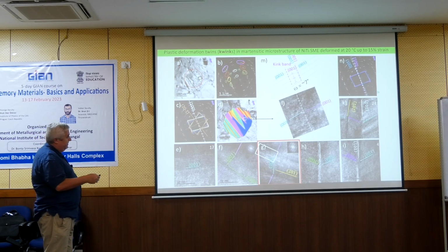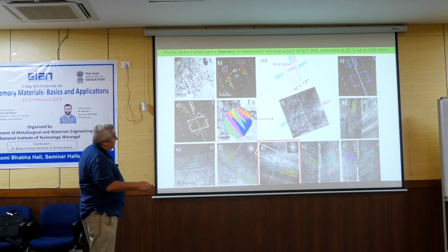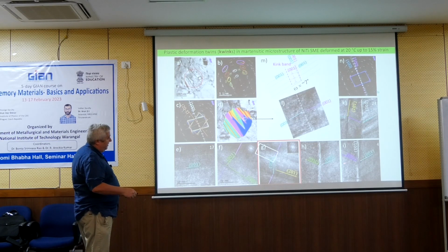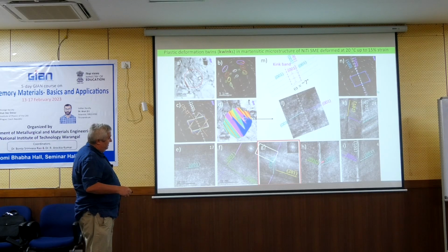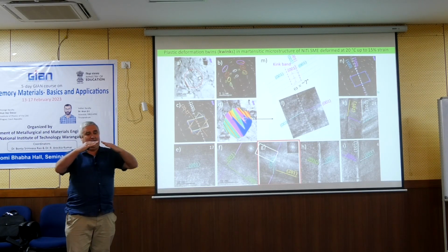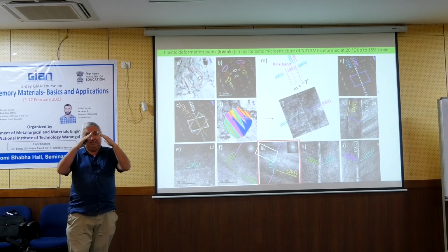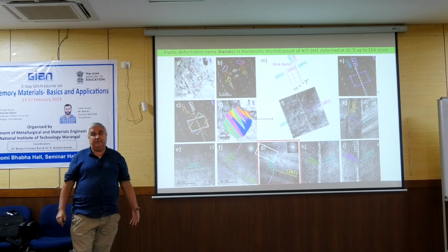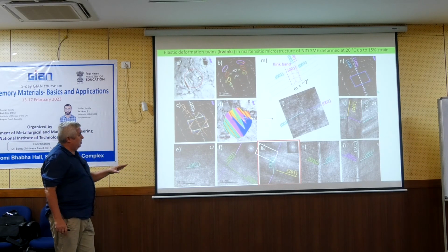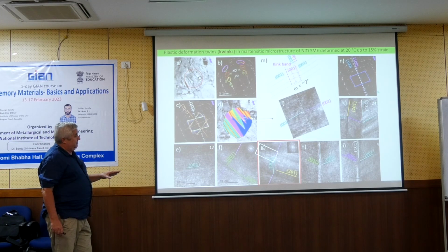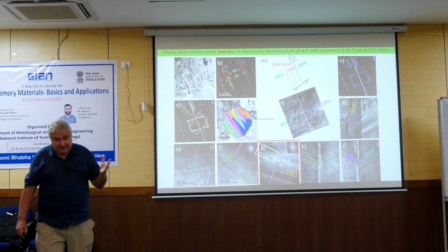And there is one striking thing. If I plot the traces of the 001 direction for every interface which is here, and we did it even more, you will find that there is a sort of mirror symmetry. So always this and this are at some kind of angle. It can be a different angle, but it's always mirror symmetry. When I looked at it, we were very surprised. What do we see? We were thinking about it. I will talk more about it later, but finally the explanation of this is very, very simple.